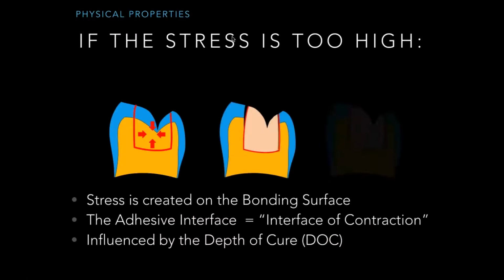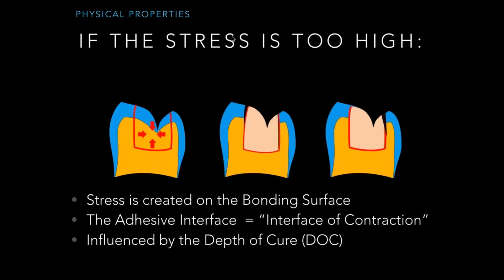Relating this clinically, we can better understand that the restorative interface is constantly subjected to stress and strain imposed by polymerization shrinkage forces, as well as thermal stimuli and, of course, functional occlusal loads. If the polymerization stress becomes high enough, it can cause cracking of the tooth structure upon light curing due to the resinous shrinkage, like you can see here in this example. Adhesive fractures may also occur, and that's called debonding. In extreme cases, the tooth may even fracture.